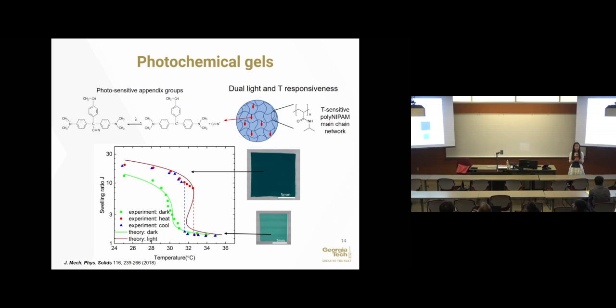So with this model, what can we do? I just give one specific example. This is a leucocyanide hydroxide molecule. And when you shine light, this bond will open up, generating a positive charge and a negative charge. Okay, it's a leucocyanide. So people couple it onto a temperature-sensitive network. So this material is both temperature-sensitive due to the main chain and light sensitive due to this light responsive molecule, okay? So what is interesting is here, when you don't shine light to it, in a dark condition, the material just behaves like a normal temperature sensitive hydrogel. When you increase the temperature, it shrinks, okay, at a particular temperature.